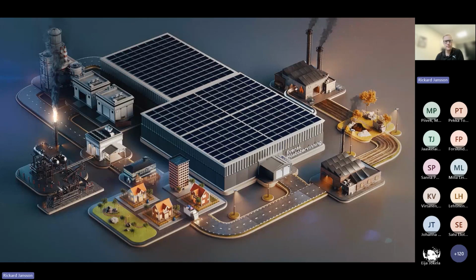This means that we need to move away from how a lot of recycling works in Europe today, where instead of keeping the quality of the recycled material, we typically downcycle it, due to these mixed polymer fractions or impurities being left in the material, which leads to us needing to find secondary applications for the material. If we mix a lot of the polymers, we will have very poor mechanical properties, which makes the recycled plastic unsuitable to replace virgin plastics in most plastic applications. So instead, the recycling industry must find secondary applications for the material. And in this case, it's illustrated with park benches being put into society after recycling, and that's because a lot of the recycled plastics actually replace timber and wood in many applications instead.